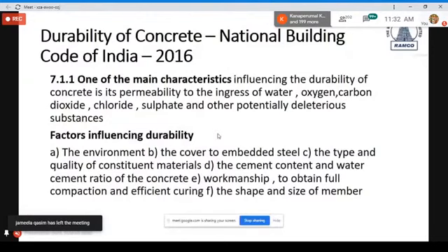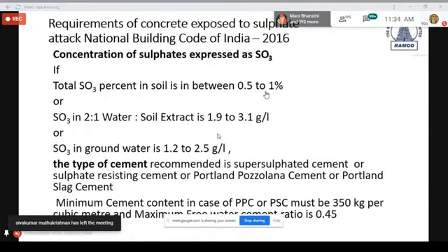You can again look this up in IS 456 2000, where if you have sulfates in soil, what happens is, we have seen during our interaction with construction professionals, when there is sulfates, immediately they will jump to the conclusion that SRC cement has to be used, without looking into the fact that SRC cement or sulfate resistant cement is poor in resisting chloride. SRC cement is only effective in resisting the attack of sulfates alone. But there is a solution for that.